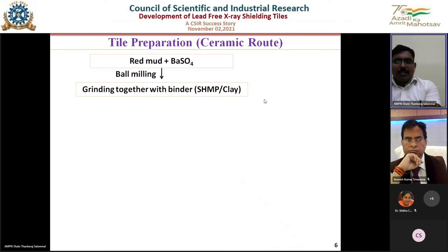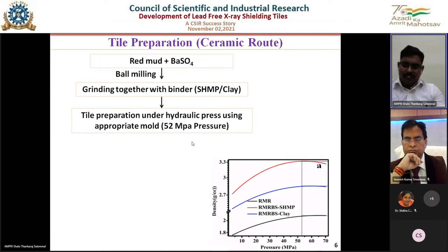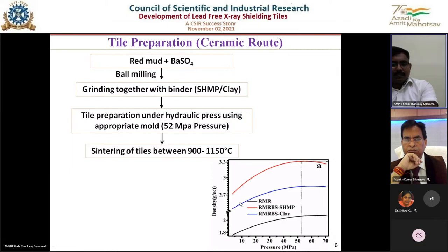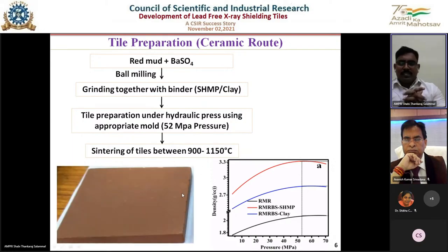Then we have added some binder, and then we made the tiles through a common ceramic route. First we apply the pressure. The optimized pressure is around 52 MPa. Then we have applied it, and then we took the tiles and sintered between 900 to 1150 degrees Celsius. And like this, we have got the final tiles.